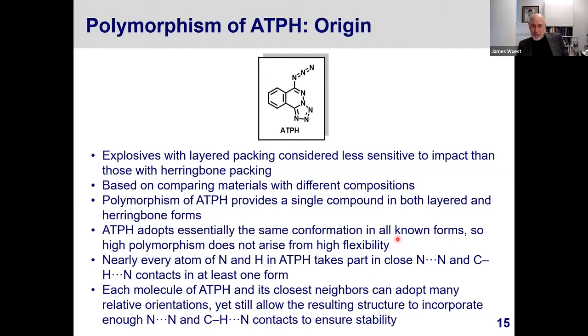So again, the conformations of the molecule in the different structures are essentially the same. So the high polymorphism is not a reflection of high flexibility. But what we see in examining the crystal structures is that virtually every atom of nitrogen and every CH bond can take part in NN or CHN interactions. So what that tells us is that however the molecule is arranged, it's possible to construct the type of key interactions that help hold the structure together.